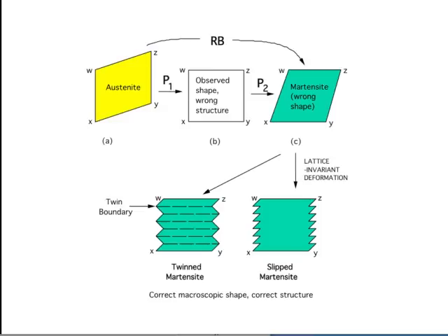Okay, so this theory completely predicts all elements of the crystallography of martensitic transformations, and it's not just applicable to, you know, austenite and martensite in steels, but to any system in which martensitic transformation happens. So, for example, in plutonium, the liquid is denser than the solid. Okay, so when the first solid forms, it's actually less dense than the liquid, and then it densifies by undergoing a series of four or five martensitic transformations between different complicated crystal structures. Okay, all that crystallography can be predicted.